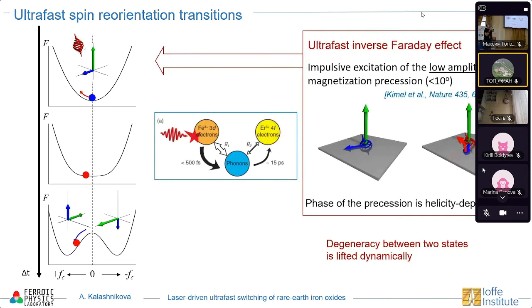If we change the polarization and use circular polarized light, then we know that circular polarized laser pulses can induce something called the ultrafast inverse Faraday effect. Briefly, when we have circular polarized light, it acts on the material as a very short pulse of effective magnetic field, and it can trigger precession. The precession will have a low amplitude of a few degrees maximum, but this means that right after the excitation, our system will start to oscillate here. So basically, it will deviate, for example, in this direction. And then when these two minima emerge, our system will prefer to go to this minimum.